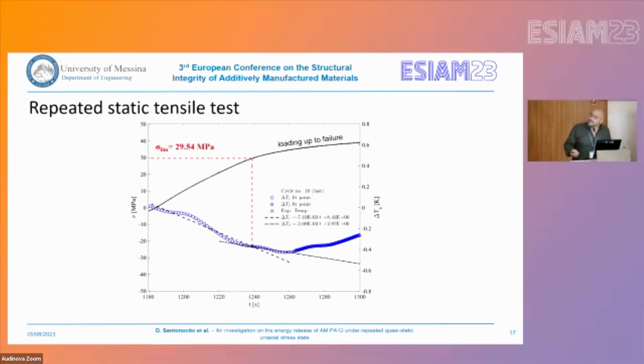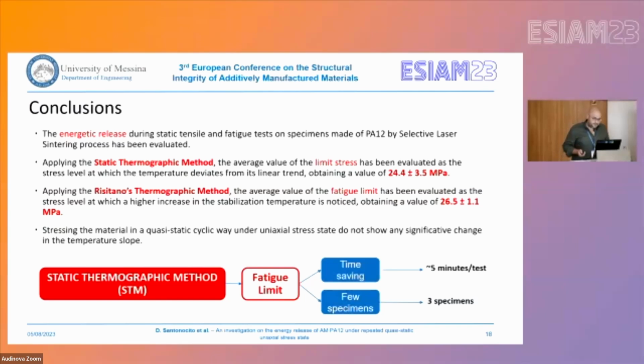At the end, in the 10th cycle, we load the specimen up to failure. So we reload the specimen and then the specimen breaks. We can assess a change in the slope at approximately a stress level of 29.5 megapascal. So in conclusion, what we have seen is that the results given by the static thermographic method are in good agreement with the Risitano thermographic method.